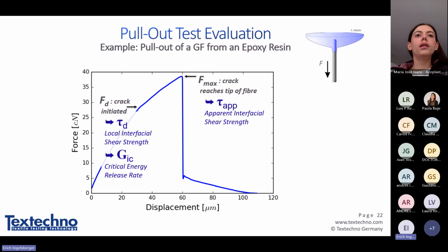With this formula, we can find the interfacial shear strength: the apparent one, from the maximum force you get by macroscopic measurements, and by analyzing the form of the force-elongation or force-displacement curve, we can find the so-called local interfacial shear strength, which is where the crack is initiated. To make it simple, the formula for the apparent interfacial shear strength is simply the maximum force divided by the wetting area, which is the embedding length we measure here, times the circumference of the fiber.